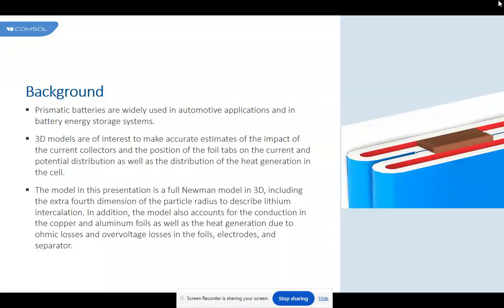The negative and positive electrodes swap their electrochemical roles as anode and cathode when the cell is charged. Despite this, in discussion of battery design, the negative electrode of a rechargeable cell is often just called the anode and the positive electrode the cathode. Its fully lithiated state of LiC6 graphite correlates to a theoretical capacity of 1,339 coulombs per gram, about 372 mAh per gram. The positive electrode is generally one of three materials: a layered oxide such as lithium cobalt oxide, a polyanion such as lithium iron phosphate, or a spinel such as lithium manganese oxide.